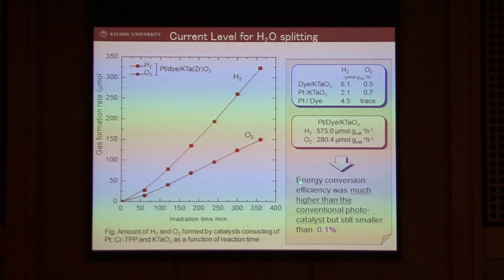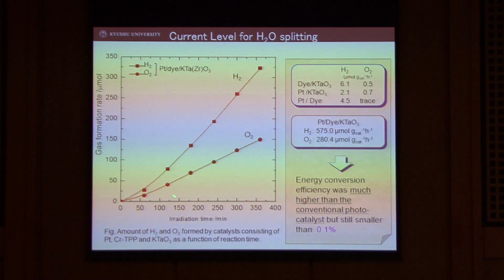This energy conversion efficiency was much higher than that of the conventional photocatalyst because of the combination with these organic dyes, but still much smaller than 0.1%. Therefore, we need to further increase the efficiency by optimizing the catalyst.